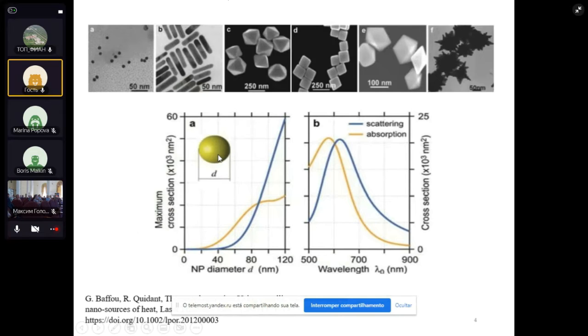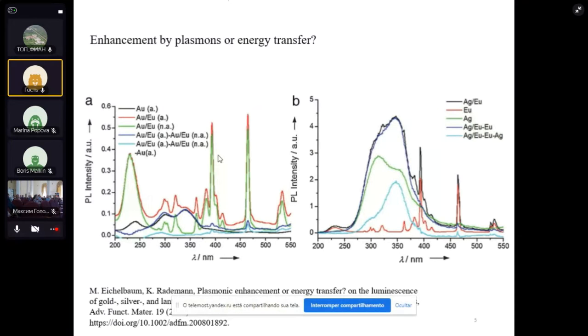The second paper that I think is relevant is by a German group. And this is important. Why? They discuss in this work the possibility that enhancement could also be produced by species like dimeric, for example, in the case of gold or silver, the enhancement could eventually be produced by dimeric Ag2, Au2 species, or Ag3, and so on, that could transfer energy to the emitting species, instead of big nanoparticles in which the plasmon effect, as we will discuss, could be important. So it is very important when we work in this subject to pay attention to this fact.